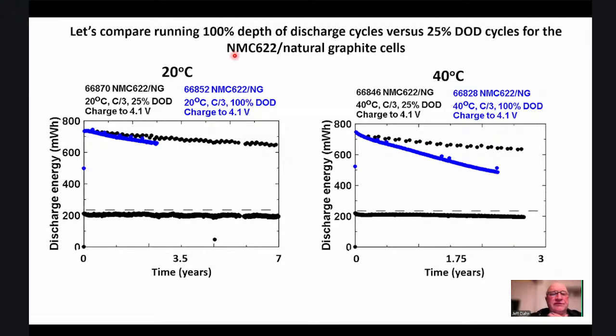So we followed these cells even further than in the paper, and at room temperature, the cells undergoing this 25% depth of discharge after a charge to 4.1 have been operating for 7 years. And you can see the checkup cycles have only lost about 10% of their original capacity in the 7 years of testing. Whereas the cells undergoing 100% depth of discharge are dying more rapidly, but still not too bad. At 40 degrees C, lithium-ion batteries lose lifetime more rapidly at higher temperature, but still the cell undergoing the 25% depth of discharge cycles has only lost 15% of its original capacity over almost 3 years continuously at 40 degrees C.